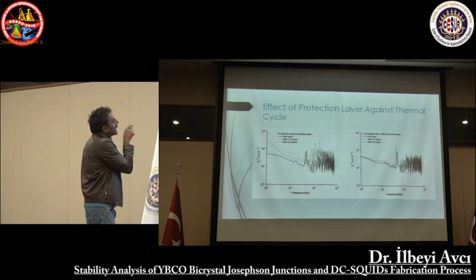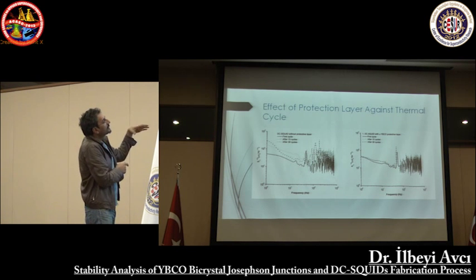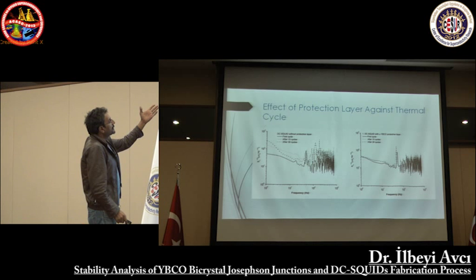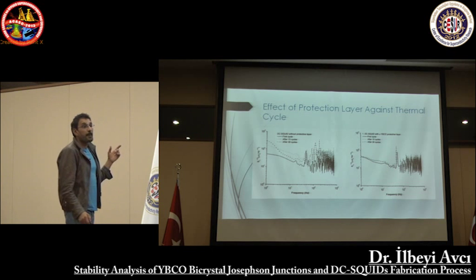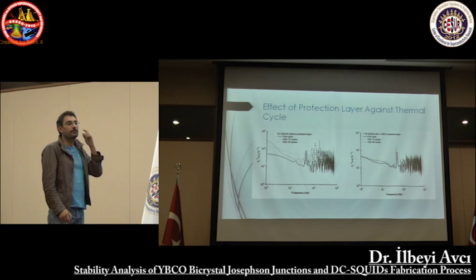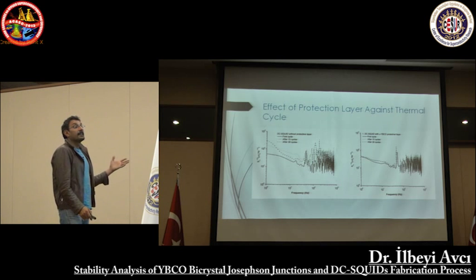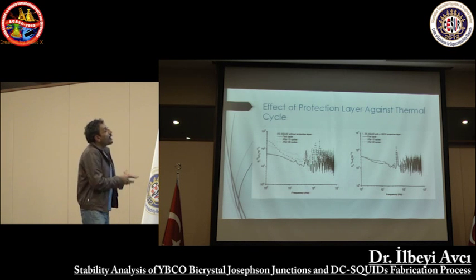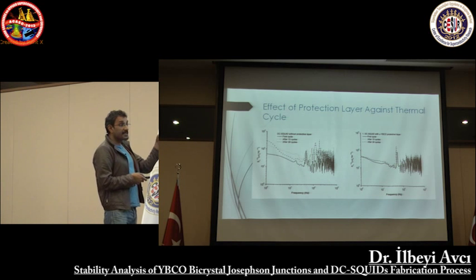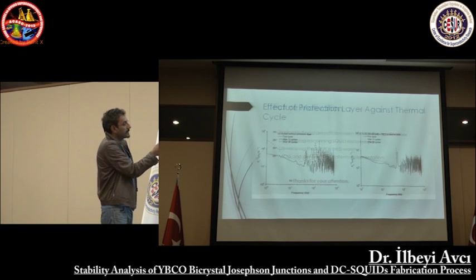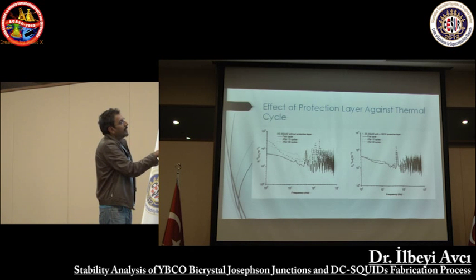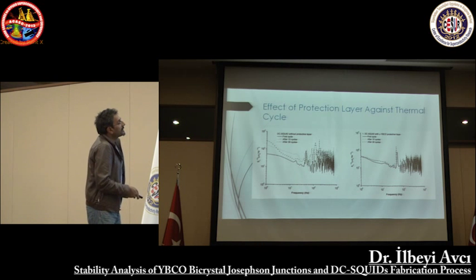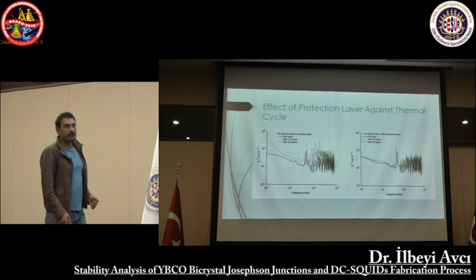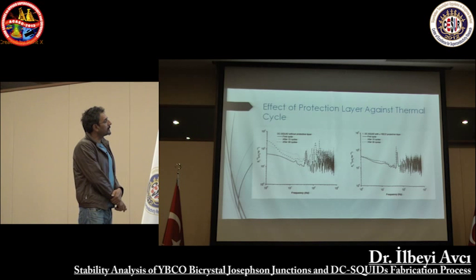The first one, as you can see, after the cycles, for example after 15 cycles, we can get degradation of the noise performance of the SQUID. After 30 cycles, it gets worse. Then, after we applied the protection layer with the amorphous YBCO, you can see this one is almost the same after almost 30 cycles. So this is what we are now applying for our DC-SQUID fabrication.